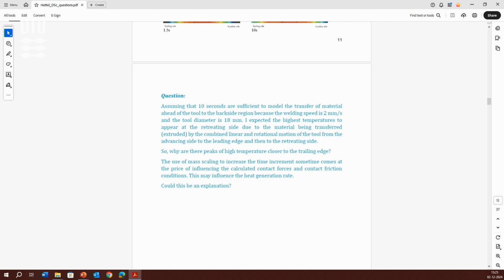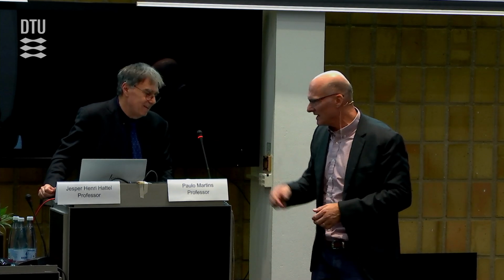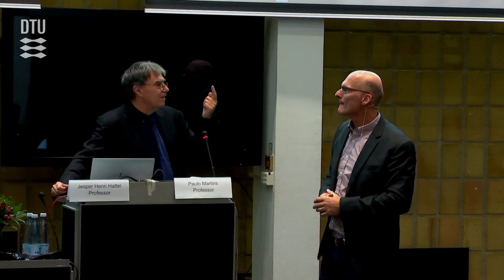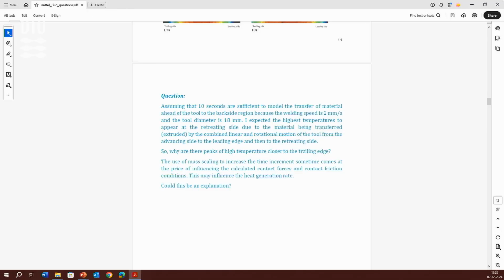What do you think? Do you think there is some effect of mass scaling? Yes. We saw that. Because there is an effect of mass scaling, a fundamental problem about dynamic explicit. I mean, of course, if you use a dynamic explicit method, you have a stability criterion with the CFL number, the Courant-Friedrichs-Lewy number, and then in the thermal calculation you have the Fourier number, right? In this case, you can overestimate the contact forces. But for sure, when you do mass scaling, it's in order to be able to use a higher time step. Yes, but it's a very nice paper.